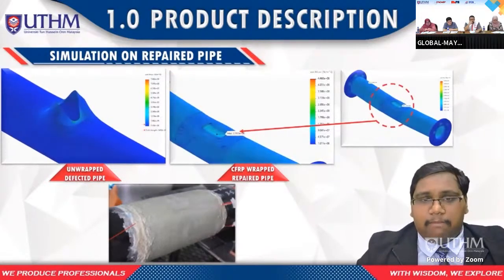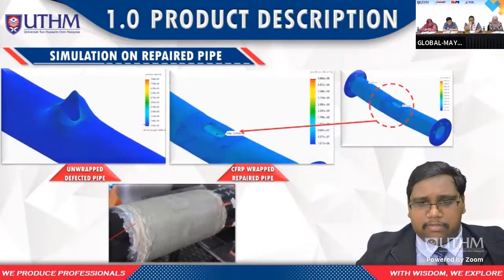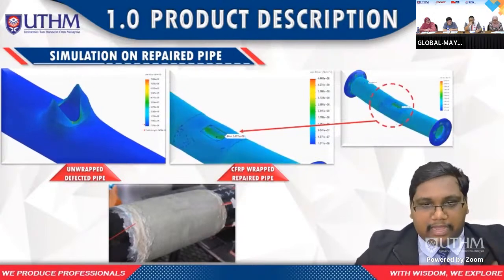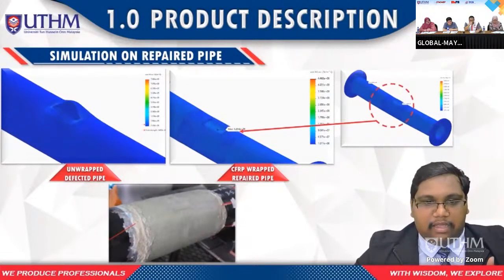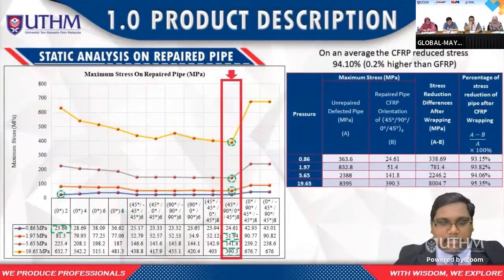And interestingly, whenever we apply the carbon fiber reinforced polymer, this case seems to be very different, whereby it will react against the pressure at the defected area. And among the simulated orientations, we found that the 45-90-0-45 degrees with 8 layers of layer orientation seems to possess a low maximum stress on the repaired pipe compared to other orientations. And at the same time, it has reduced 94.10% of stress on average, which is 0.2% higher than glass fiber reinforced polymer.